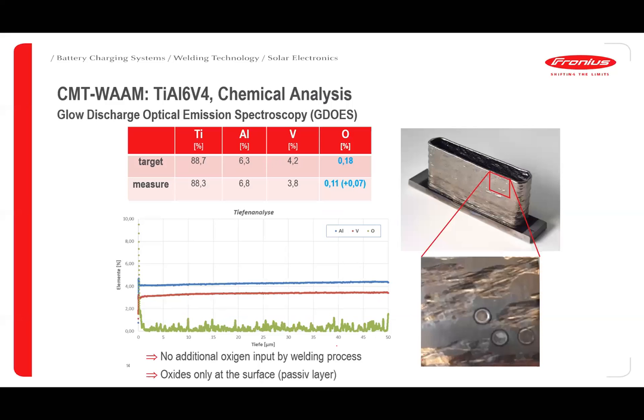So coming to the next study, generally what happens is all these elements like titanium, aluminium, magnesium, all those alloys have a very high affinity towards oxygen. So we wanted to study what is the level of the oxygen content in this particular component. We made a component which is shown on the slides, where we have achieved close to around 0.11 vis-a-vis the target, which was supposed to be 0.18.